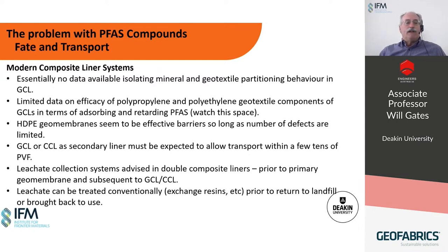Again, to reiterate, leachate collection systems should be advised, and we strongly advise double composite liner systems where the primary geomembranes and subsequent geosynthetic clay liner systems work in tandem. And the leachates in the leachate collection systems should also be considered to be treated for removal or destruction of the PFAS. So you're basically over time reducing the load in that landfill.